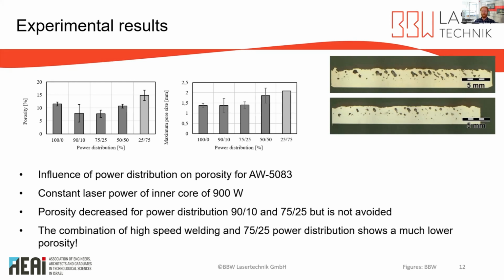In the right figure, there is a comparison of two longitudinal sections with a power distribution of 100 to 0, so 100% of power in the core, and 75 to 25%. And you can see here very good what I already have told you, that the porosity is clearly decreasing.